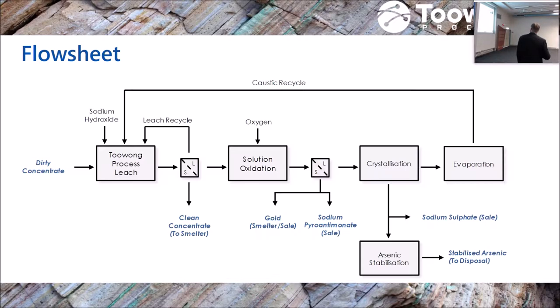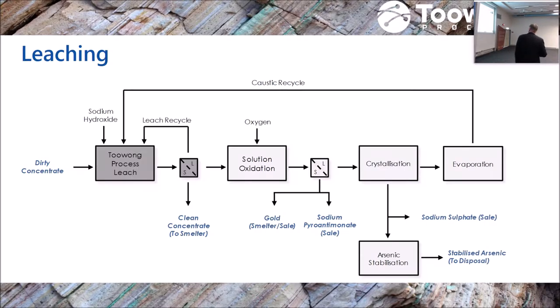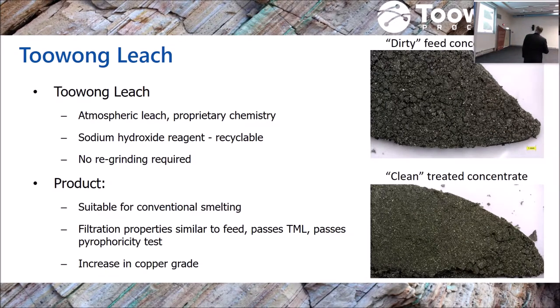Clean concentrate comes out here. Basically, dirty concentrate, clean concentrate. Anyone that's been involved in hydromet processes will always get a little bit nervous that when you leach something, the residue coming out of the leach circuit is difficult to filter and horrible, which is generally true. In this process, because we're only selectively leaching a very small fraction out of the concentrate, and the caustic basically reprecipitates a bit of aluminium and silica that leaches and almost makes like a conglomerate, the residue filtration is usually better than the feed, and it's certainly no worse.